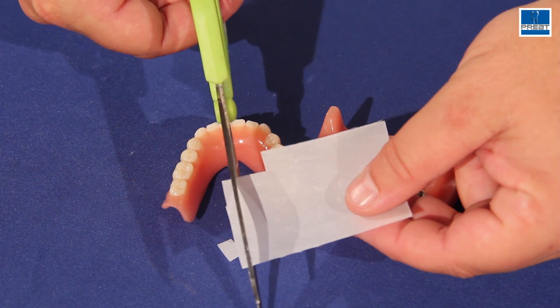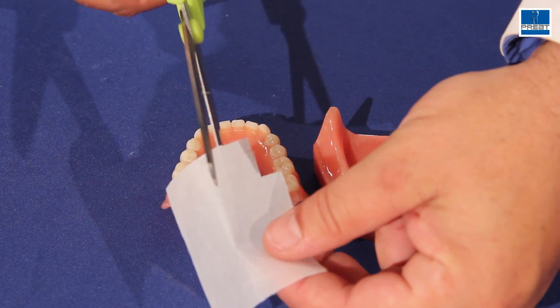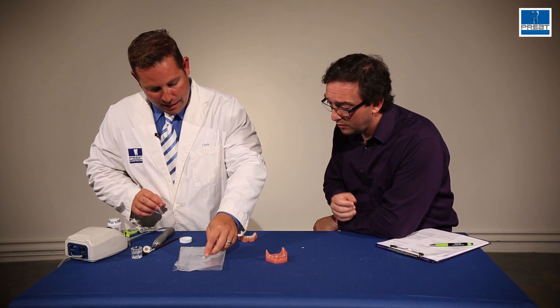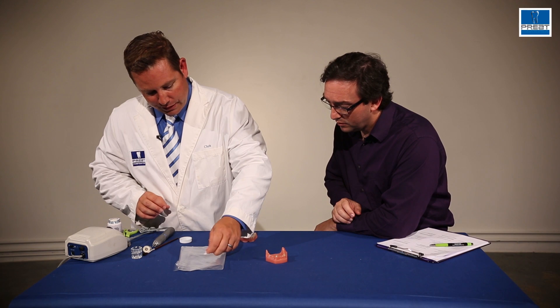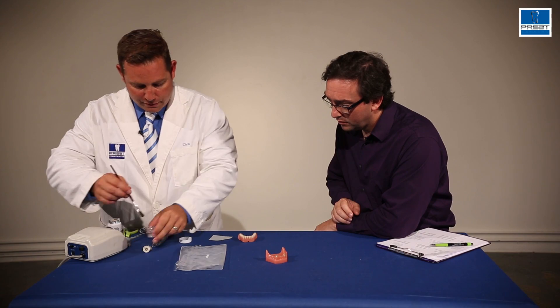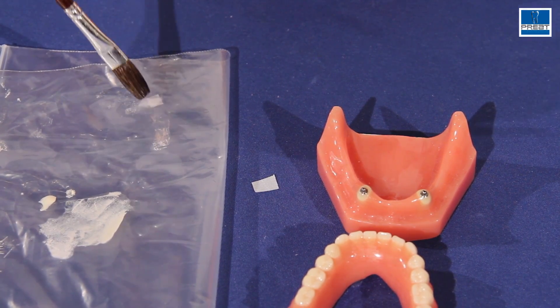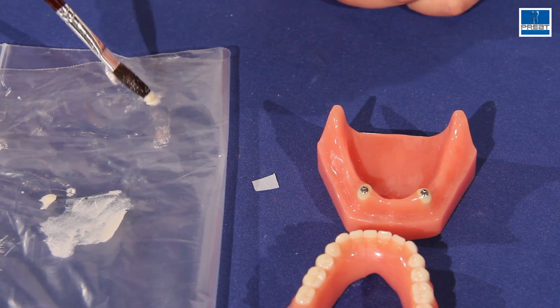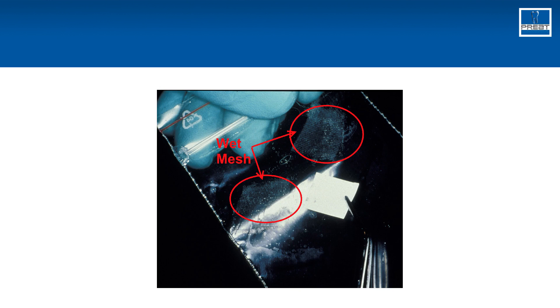The first thing we do is cut up a couple of small pieces of the mesh. Then I have a little bit of a mixture here of monomer and polymer, and I'm wetting these pieces on a nice clean surface. I'm just going to paint it — this is all you need to do to wet it. You just dab it with a little bit of monomer, then sprinkle a little bit of polymer, and you'll see how the mesh has gone from white to translucent.